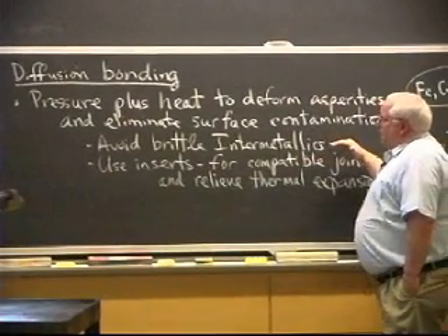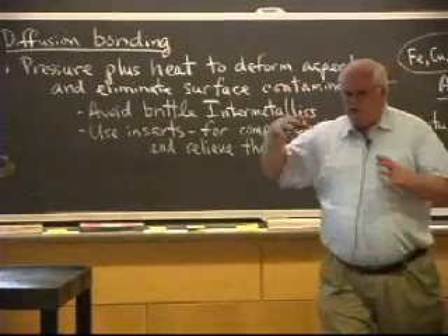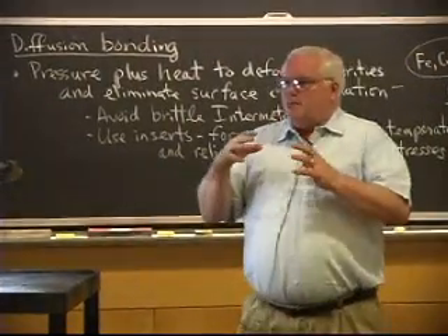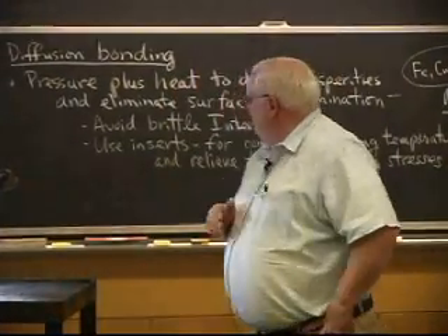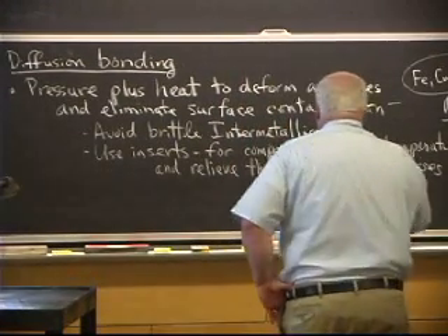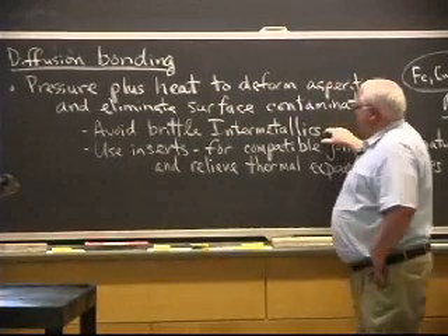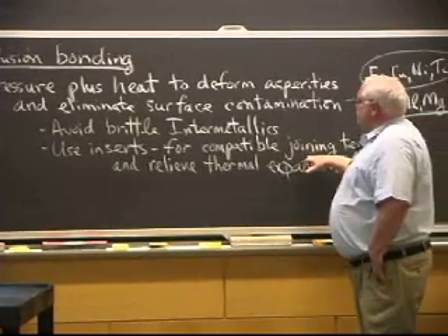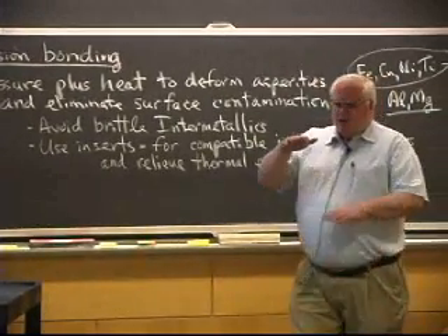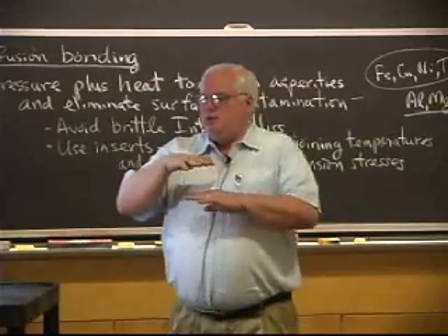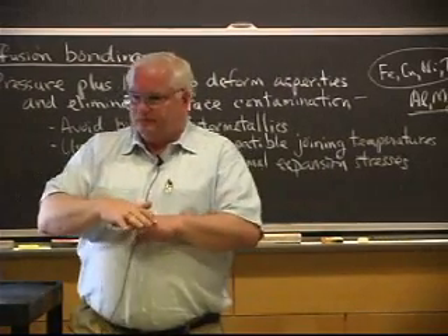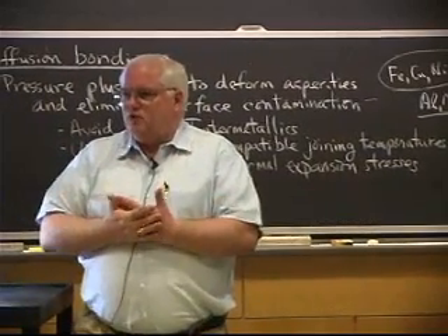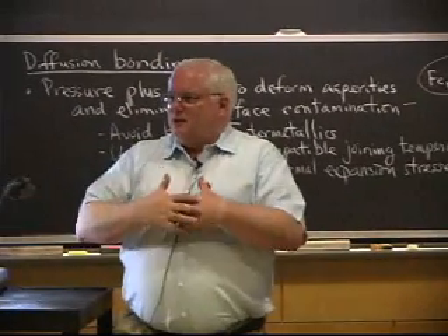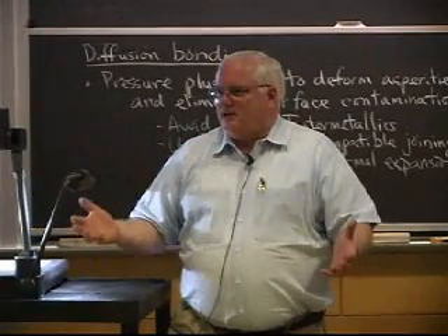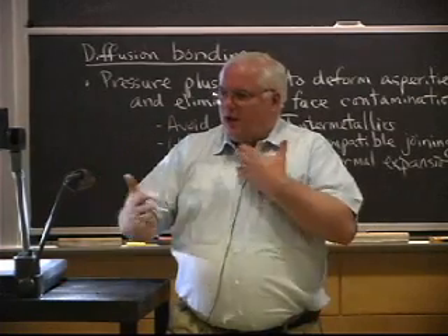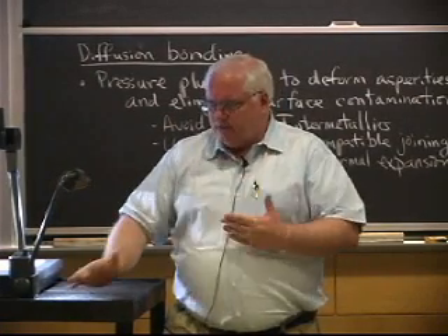One of the things you have to worry about is formation. When you're doing all this, things are diffusing, the atoms are moving, and I might form brittle intermetallics. I'll give you an example later when we get to transient liquid phase diffusion bonding tomorrow. You use inserts sometimes, because a lot of times diffusion bonding is very good for joining 2 dissimilar materials. And a lot of dissimilar materials you can't just fusion weld because in the liquid state they're going to end up forming an alloy that doesn't have decent properties. So you like diffusion bonding because it's a solid state process.